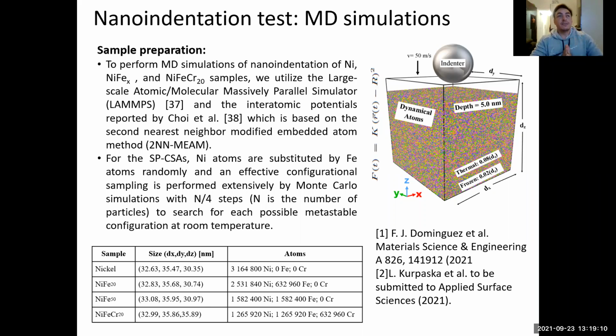So we spent some time to prepare the sample, and then we define the sample because we are going to do an MD simulation by using a spherical indenter. And now again, in the experiments, they are doing the experiments with a Berkovich tip. If some of you don't know what a Berkovich tip is, it is something like a cone, and it has different geometries in this part. But the tip of the indenter has roundness. So according to the time scale and the space scale of the simulations, we can model the Berkovich tip as a spherical indenter tip. My friends in the laboratory also have spherical tips.